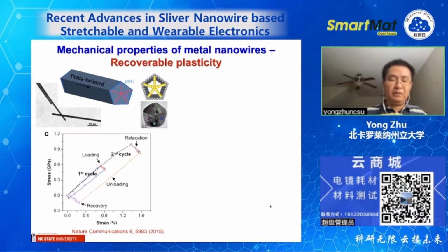I was talking about how the properties can be different, so I will give you one example for mechanical properties. Mostly the silver nanowires we use in solution synthesis are pentatwin nanowires, because you have five twin boundaries along the length of the nanowire. So the cross-sectional TEM clearly shows the five twin boundaries.